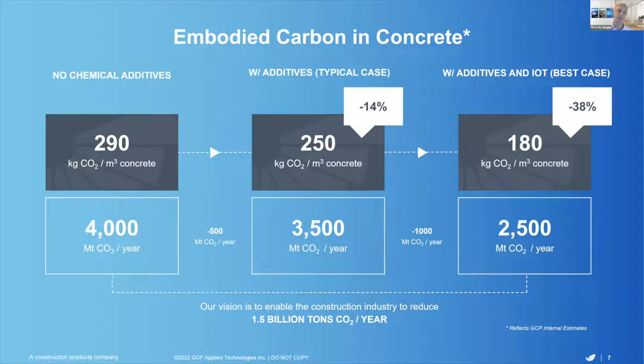The last high-level numbers I have for today: we tried to summarize in a simple visual way what it means to utilize cement additives and concrete admixtures from a global perspective with a focus on CO2 emissions. Today, we estimated that the typical concrete mix could emit approximately — as the median — 250 kilograms of CO2 per cubic meter, a very broad range between 100 and up to 600 or more kilograms per cubic meter. If you take this as a typical case study, and multiply it by the 14 billion cubic meters produced annually, you get to approximately 3.5 billion tons of CO2 per year from concrete.